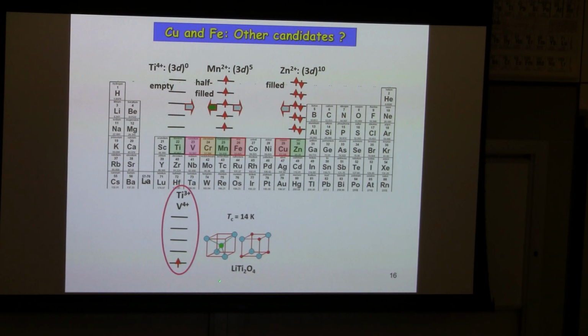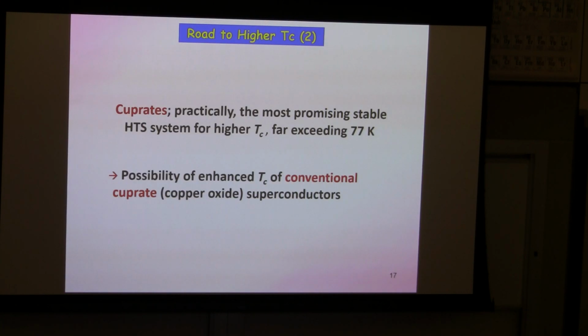Actually, a very old known material, titanium oxide, which has a spinel structure, shows surprisingly high Tc values. That was almost 40 or 50 years ago. But apparently, oxide is not a suitable partner of titanium or vanadium, because we cannot expect very strong covalent bonding or very strong superexchange coupling in the case of titanium oxide or vanadium oxide. So we have to look for a more suitable partner other than oxygen. Okay, this is the first route I would like to propose to you.